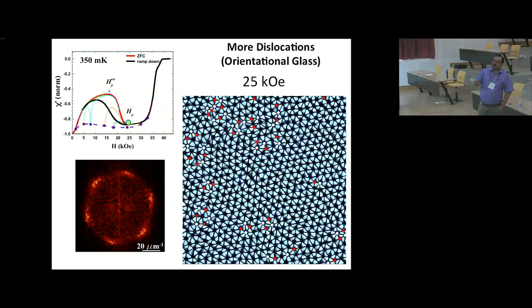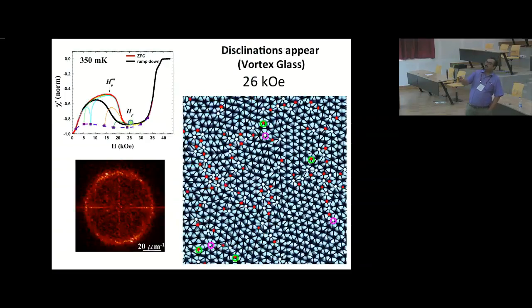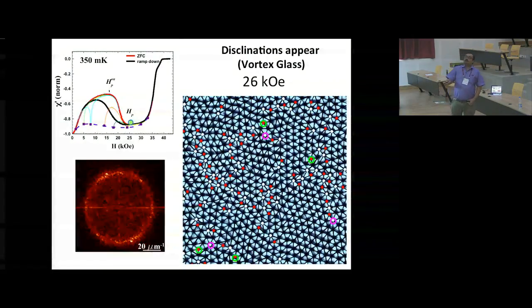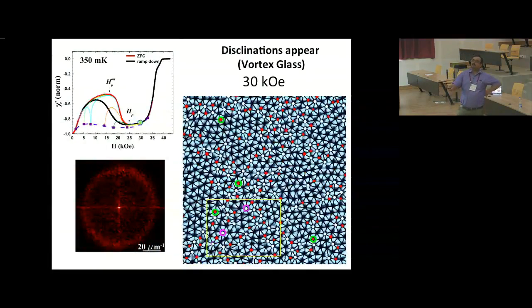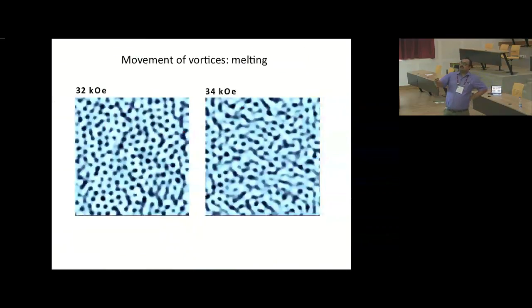Then I cross the peak of the peak effect here. And what I start seeing is these new kinds of defects, which are isolated 5-fold and 7-fold coordination points. So these are not bound pairs, they have become unbound. And now you see the Fourier transform is an isotropic circle. So I have destroyed my orientational order also. And then if I go further up, it gets further diffused, but both the orientational orders are lost. And it's only very close to HC2 that I see signatures of vortices moving, and that is why here you cannot identify individual vortices, but they become streaks because they are moving, and we are doing a measurement that's very slow. And this is possibly close to the liquid state.